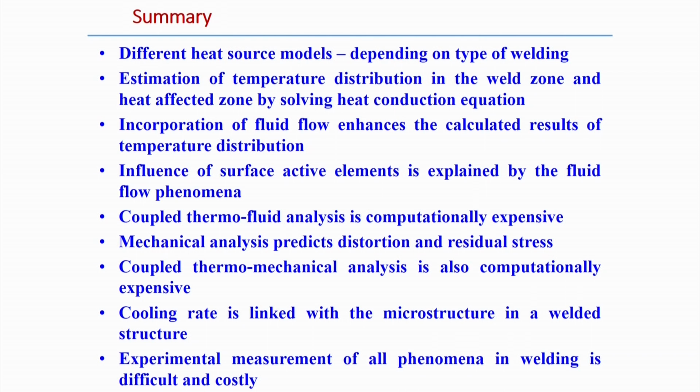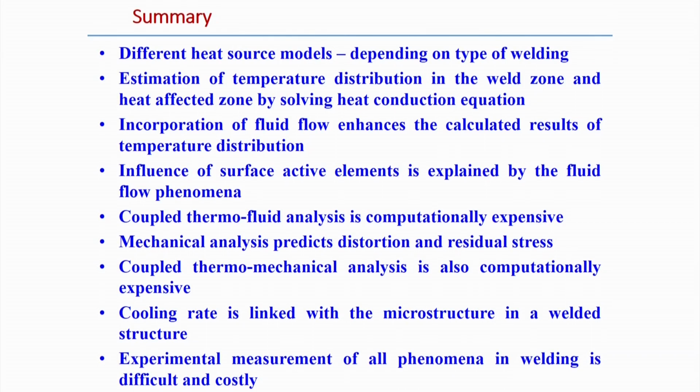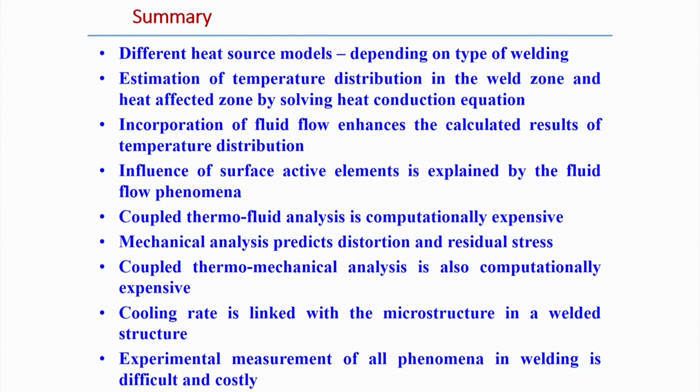Next was estimation of the temperature distribution in the weld zone and the heat affected zone by solving heat conduction. We have discussed that the temperature distribution can be obtained by simply solving the heat conduction equation with proper boundary conditions. Of course, incorporating fluid flow gives more precise temperature distribution results, and material flow is better represented if we consider fluid flow in the welding process as compared to only heat conduction analysis. The effect of surface active elements is also better explained by incorporating fluid flow phenomena in the weld pool simulation. But the point is that coupled thermo-fluid analysis is computationally very expensive. So, in most cases we neglect the fluid flow analysis and do only the heat conduction analysis.